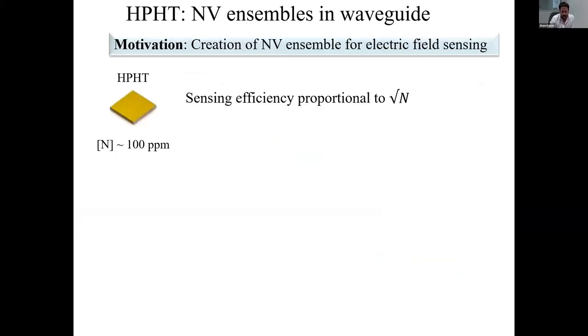Another application, so the application of single NVs is more compelling for quantum information. The next step would, of course, be to build up a three-dimensional network of interconnected quantum bits for quantum information. Another exciting application is quantum sensing. In this case, we want to work with a lower grade diamond sample made with HPHT. And the reason for that is because it has a higher concentration of nitrogen impurities, and therefore we expect to be able to form a higher concentration of NVs using this laser exposure.